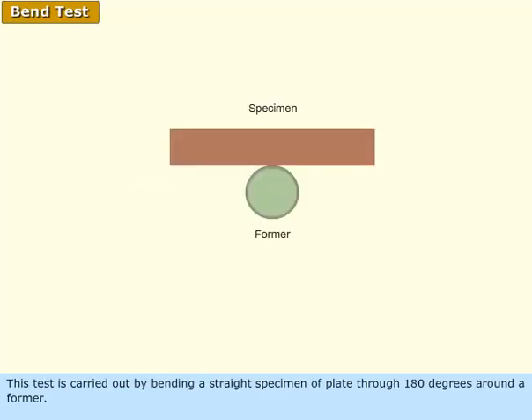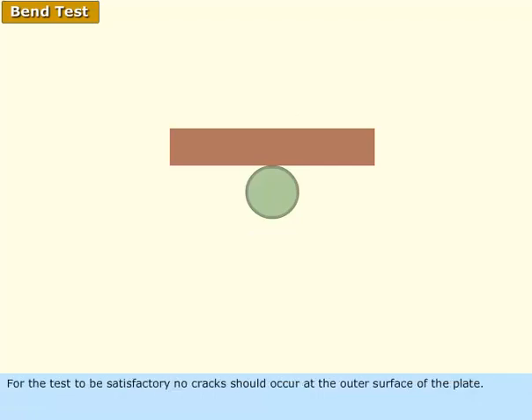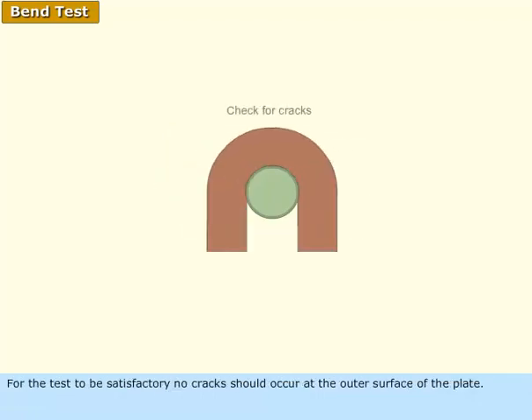This test is carried out by bending a straight specimen of plate through 180 degrees around a former. For the test to be satisfactory, no cracks should occur at the outer surface of the plate. The significance of this test is that it is carried out on boilerplate materials, because a boiler is a fired pressure vessel.